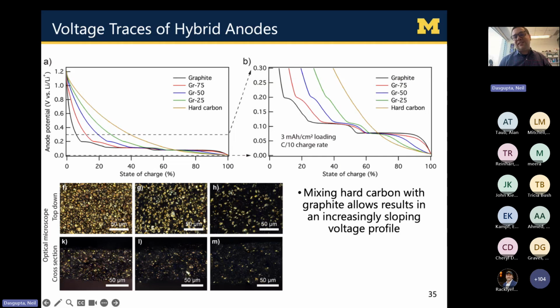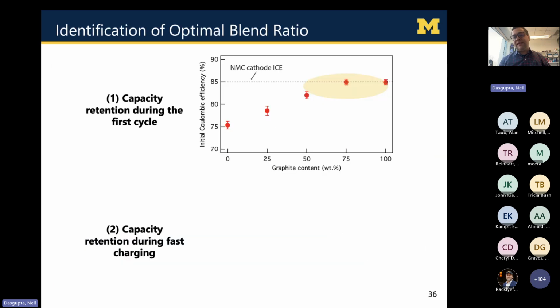And while there's a lot of information at the top that I won't go into detail on in terms of the voltage trace, we saw some very interesting trends in the shape of the voltage versus state of charge with respect to blending this hard carbon in. But let me cut to the chase of the end result here. So what we see is that if you have 0% graphite, 100% hard carbon in your electrode, you lose, as I said, about 25% of the capacity in the first charge cycle. If you look at the other end of this graph, if you have 100% graphite and 0% hard carbon, notice we're still losing about 15% of the accessible capacity after the first formation cycle.